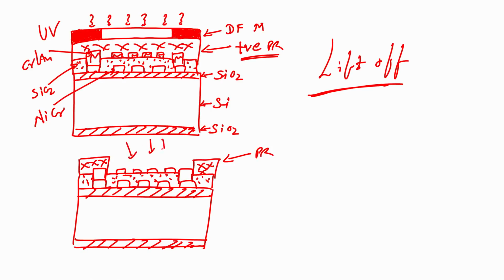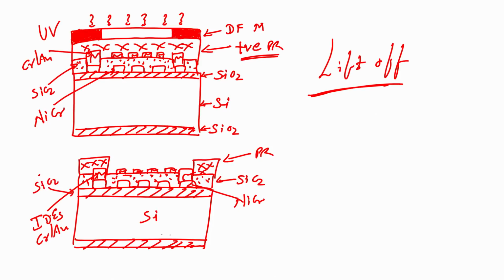In this region there is nothing, you can see there is no photoresist, right, but here there is photoresist and we know what this one is: interdigital electrodes, right, interdigitated electrodes made from gold, or you can say chrome gold, nichrome, silicon dioxide, silicon dioxide, right. Now, I will go for hard bake, 120, 1 minute on a hot plate. After hard bake, next step is I will deposit a piezoresistive material. Piezoresistive material will be deposited like this, right. So, let me just draw the piezoresistive material with a different color.